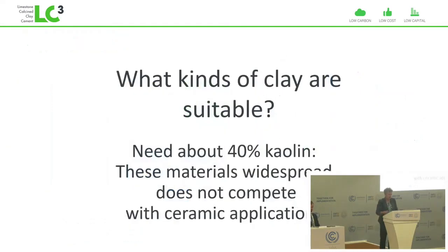So our key question at the beginning of this work was really to identify what kinds of clays. And this is very important because we found we only need about 40% of this mineral we call kaolin. We don't need very pure clays. We just need really common or garden clays you can find everywhere. And so this does not compete with other applications. This is another misunderstanding a lot of people have.